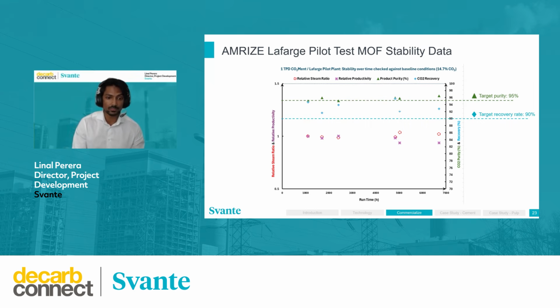Initially, you can see that we're not only able to meet, or in some cases exceed, the target performance that we were looking to achieve within this test campaign. Most importantly, through continuous operation of up to 7,000 hours, we do not see any degradation in performance. We are able to maintain our performance over each parameter over the course of this test campaign, which is how we validate that the filters themselves are stable to the contaminants that are in the flue gas that we see in this pilot plant.